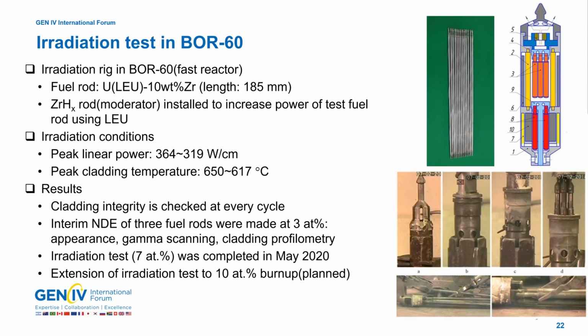And we also did an irradiation test in the fast research reactor BOR-60 in Russia. For that we fabricated about 12 fuel rods in our institute, and then transported these fuel rods to the BOR-60 for the irradiation test. During the irradiation, the peak linear power changed from about 364 to 319, depending on the reactor operation conditions and the fuel rod positions. The peak cladding temperature is about 650 to 617 centigrade.